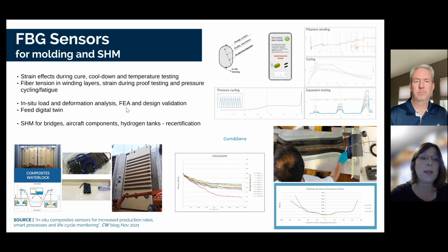And one of the reasons they do that is so that they can look at what happens with load and deformation of the lifetime of the structure. Also, like I showed with the rudder, they used that for design validation and validation of their FEA. But one of the other things that I find interesting is you can use these for flow monitoring. I wouldn't have thought that you could use this kind of sensor for that, but basically there's a change in the strain as the resin comes through, and/or temperature, and so you can actually see the position of the resin.